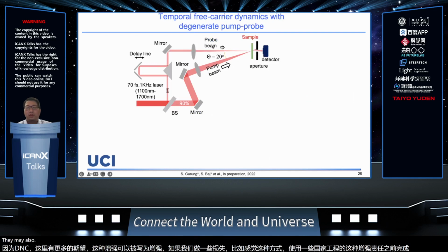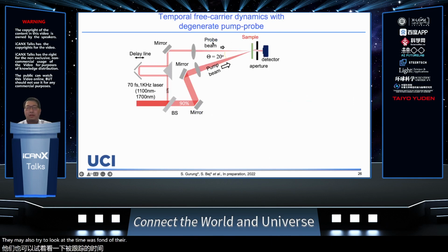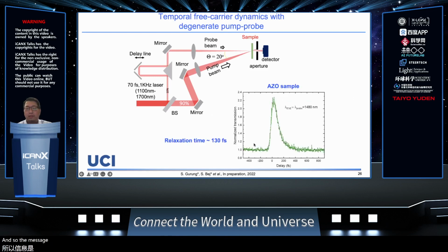And we also try to look at the time response of this. So we try to use a standard pump-probe technique and try to measure the time response. This typical delayed response you can see. So we have a relaxation time of around 130 femtoseconds, which means quite a fast nonlinear effect in this type of ENZ material, which is quite important because you want to enhance the nonlinearity and at the same time also have a quite fast response as well.